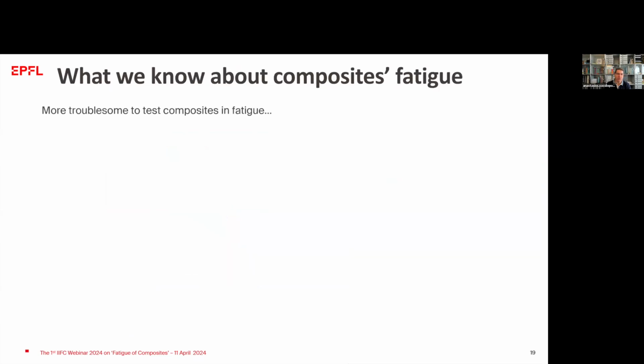So what do we know about composite fatigue? We know that it is more troublesome than fatigue for metals. When we test, we have heating of the material, so we need to test at low frequencies, which means we need to spend more time testing composites. We have problems when we test multi-directional laminates or angle ply laminates. We have reorientation of the fibers due to the loading, and this actually changes the material. So we are testing a material that is changing during loading, and we have to consider this as well.